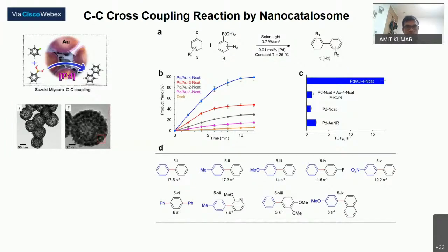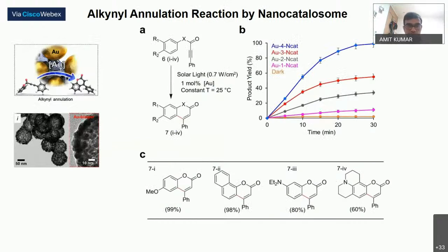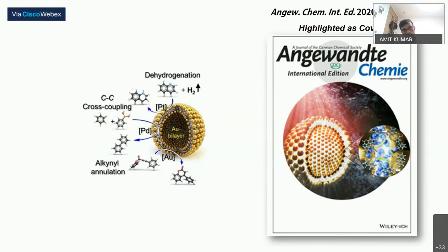The third reaction we tried is the alkynyl annulation reaction, which is a cyclization reaction, gold catalyzed cyclization reaction. And this kind of cyclization generates various fluorescent molecules, which are actually very useful for bioimaging applications. So using versatile customization of these kind of plasmonic bilayer structures, we can perform different kind of chemistry. This paper was published in Angewandte Chemie, and it came as a main cover of the issue.